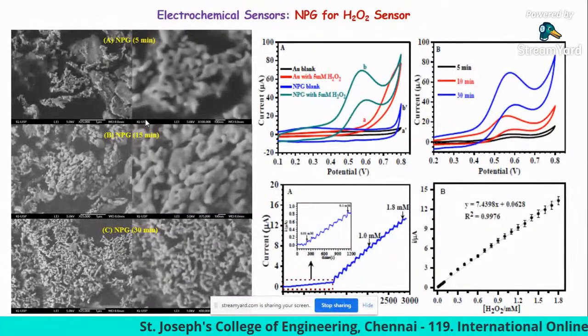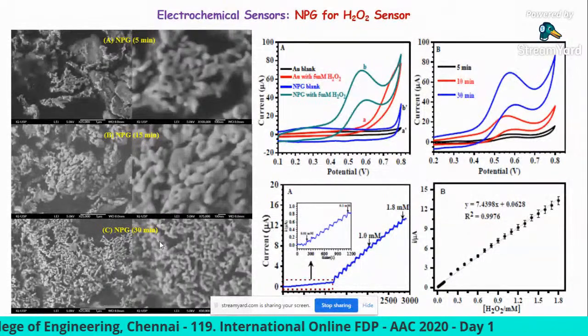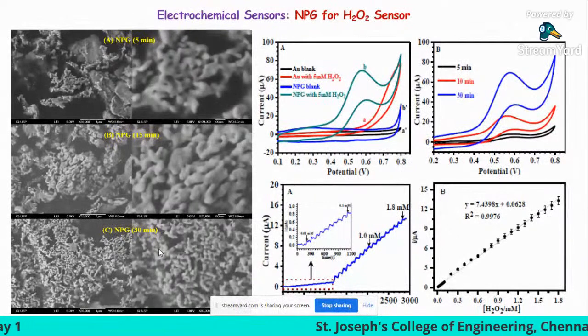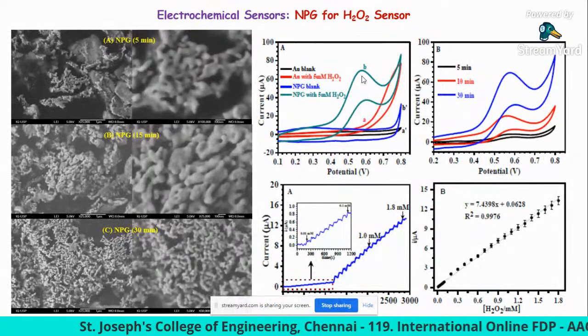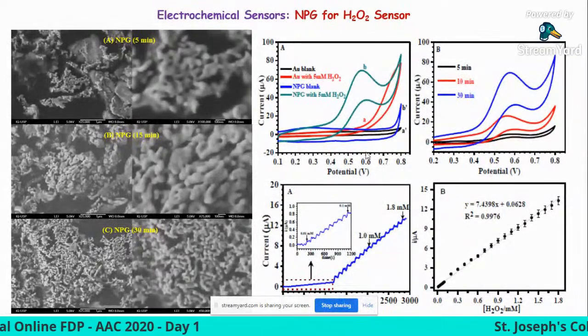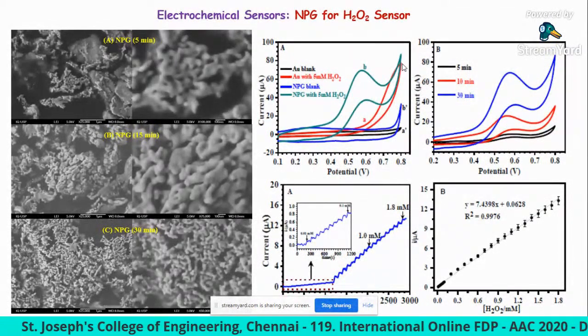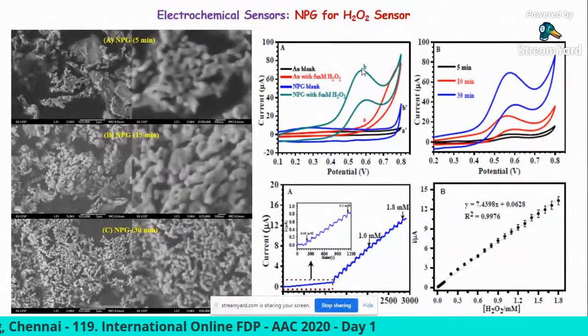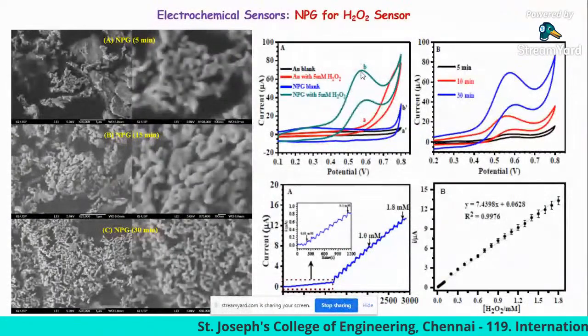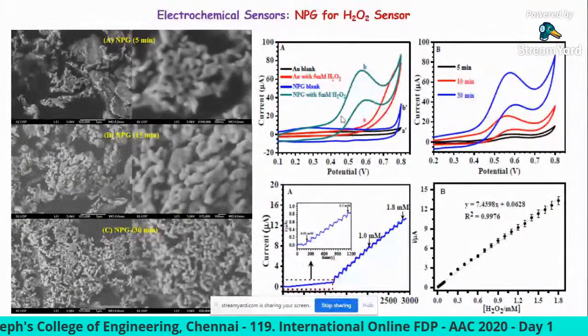Here we prepared the nanoporous gold at different anodization times: 5 minutes, 15 minutes, 30 minutes, and so on. Then we used it as a hydrogen peroxide oxidation sensor. You can see the hydrogen peroxide oxidation takes place for nanoporous gold at plus 0.6 volt. However, the red line is the hydrogen peroxide oxidation at the bare gold electrode. Here also there is a clear shift in the peak potential, and at this potential there is no current signal for bare gold, but in the case of nanoporous gold, there is a clear current signal. So this shows the nanoporous gold is also suitable for hydrogen peroxide oxidation.